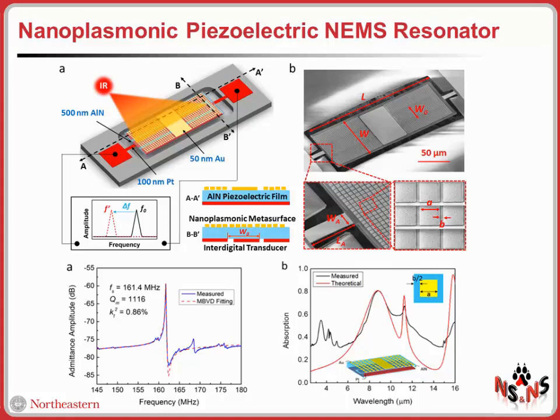One with these nanoplasmonic structures that we use to confine the electromagnetic radiation in the body of this piezoelectric structure, and also a continuous metal plate, which is used to improve the confinement of the excitation electric field provided by the bottom electrode. As you can see, the device here is quite thin, and it's again connected to the substrate using those tiny metal anchors that I described before. Given this particular design, we measured again a relatively high quality factor, above 1,000 for this prototype.